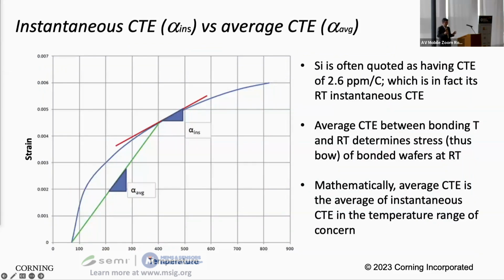A little bit on CTE because it can be a confusing concept. Most people cite silicon CTE to be 2.6 ppm per degree C, but that's actually what's called the instantaneous CTE. This is when you vary the temperature close to room temperature a little bit, and then you watch the strain or the relative length change, and then you take the ratio, which is essentially the tangent, the purplish reddish looking line. So that's your instantaneous CTE. If you bond at a certain temperature and you cool back down to room temperature, what's more relevant is the green line. This is what's called the average CTE. So this is the overall shrinkage of two materials, and you really want the average CTE to match.